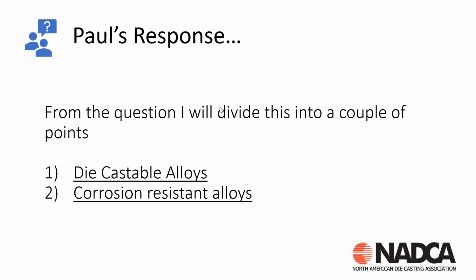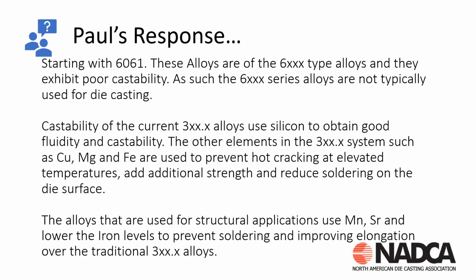And the first one is going to be, what are die castable alloys? What makes a die castable alloy? And then I'm going to talk about corrosion resistance of those alloys. So as we start looking at casting or alloys in general, 6061 is aluminum, obviously. And those alloys are considered the 6000 series, 6XXX series type alloys. And they typically exhibit poor castability. Okay, so these 6000 series alloys are not typically used for die casting because of their poor castability.